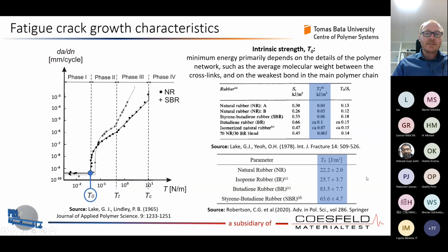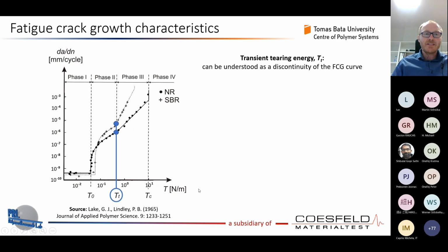So that is what we did as well, and Chris introduced it even in his presentation. We repeated this analysis and determined the T0 values with our intrinsic strength analyzer, and they are very close to what Lake and Yeoh published in this history, let's say. And the same ranking: the largest has butadiene rubber, the lowest natural rubber, and in between is styrene butadiene rubber.